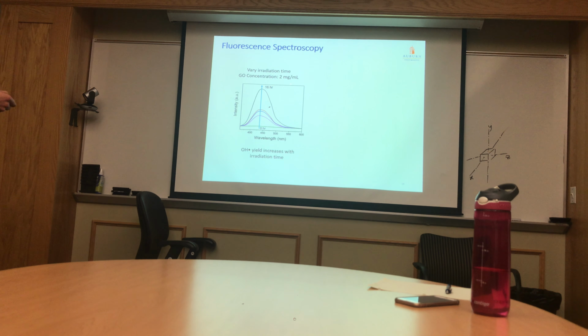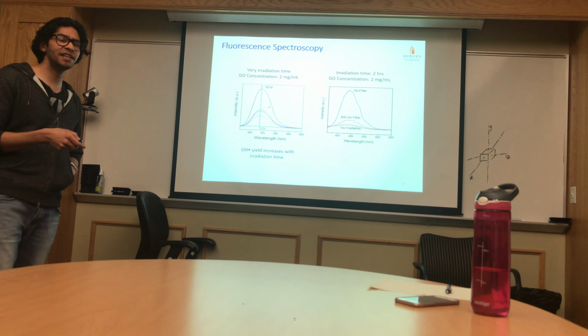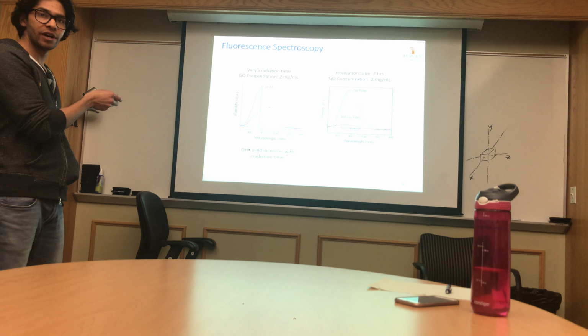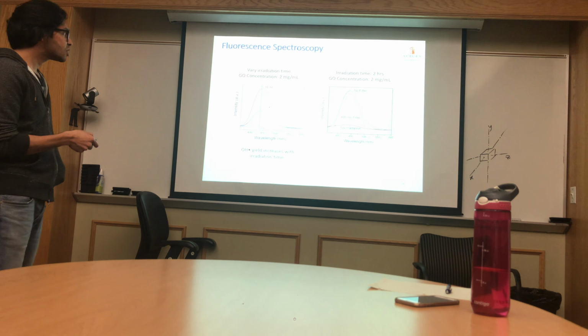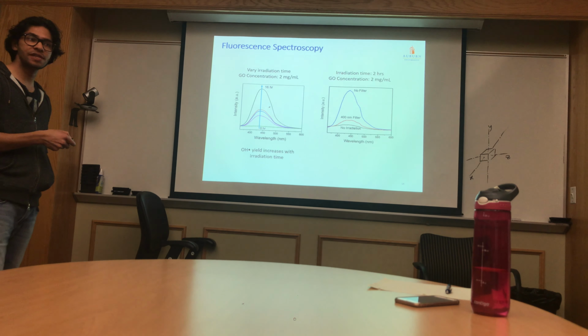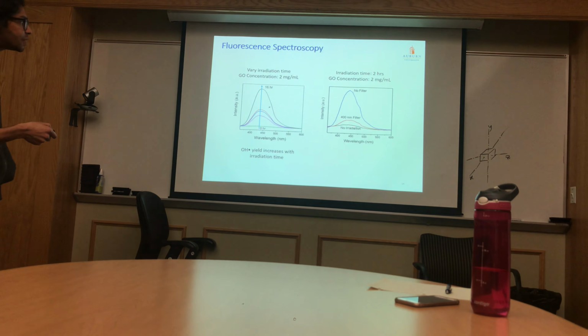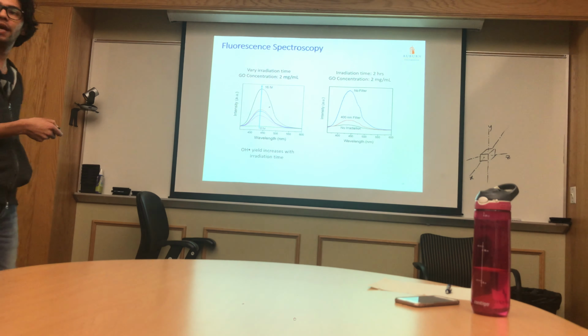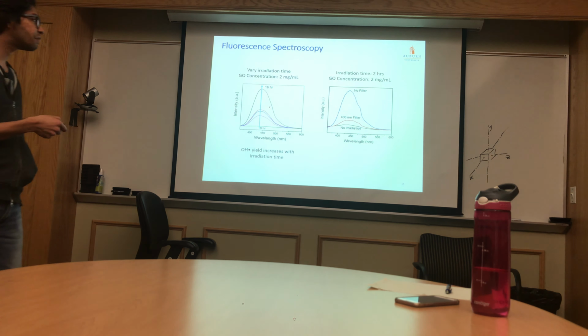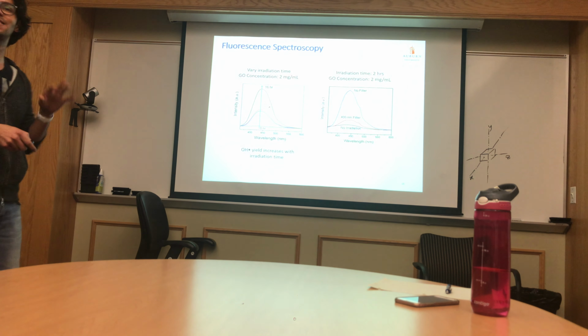Now after that, we wanted to know whether this photoreduction is caused just by the UV spectrum, or whether visible light is also responsible for the photoreduction. So we applied a 400 nanometer pass filter. What it means is it allows wavelengths only above 400, that is the visible region. So we see, yes, there is fluorescence. However, this fluorescence is only 20% of the one without any filter. So the extent of reaction is very slow, but it's still there.